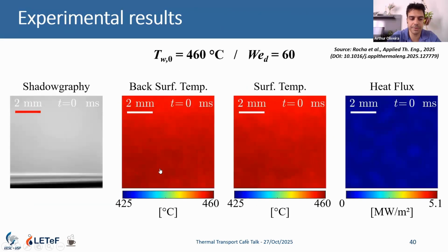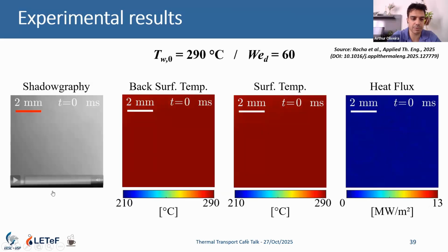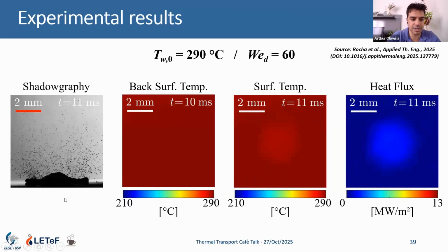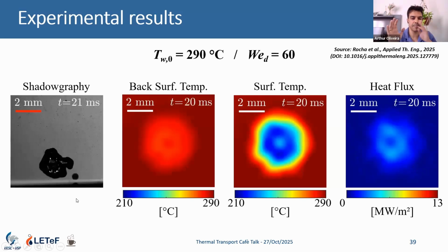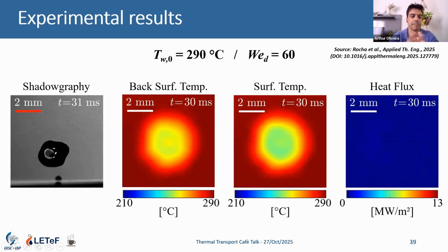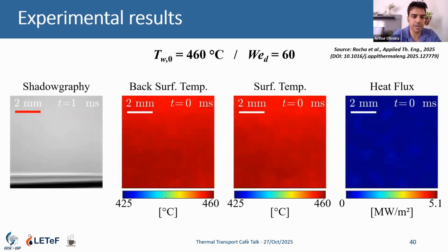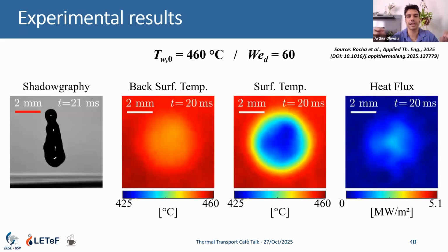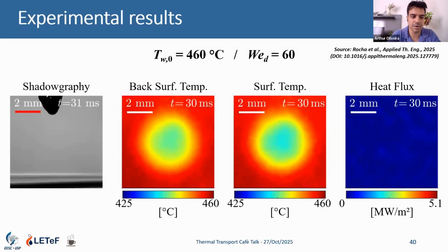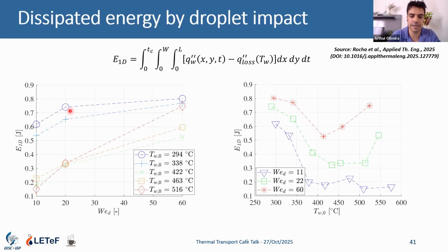That can be seen here in the video. When I launch it, you can see in the shadowgraph images a lot of atomization, which is only possible because we have bubble nucleation during the droplet impact. But for the other condition, at high temperature, we have droplet rebound, so the vapor layer thickness is already established, so we can expect this kind of minimum.